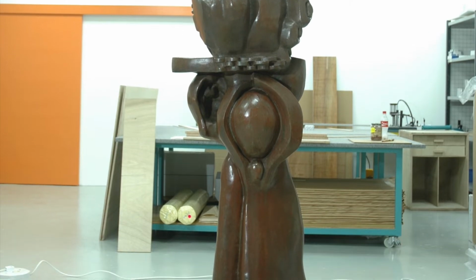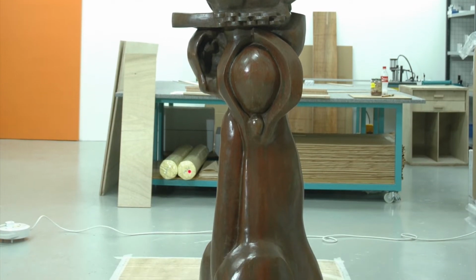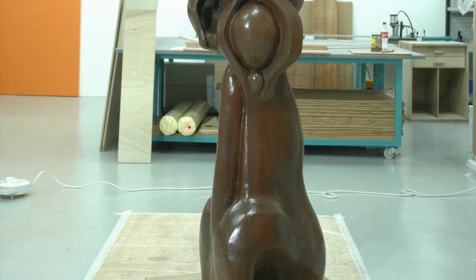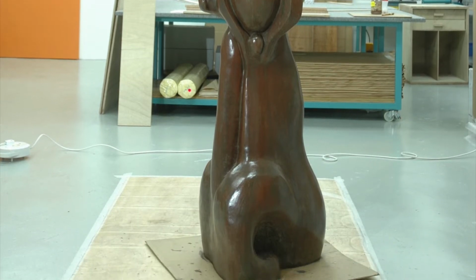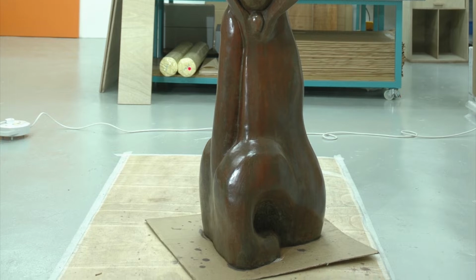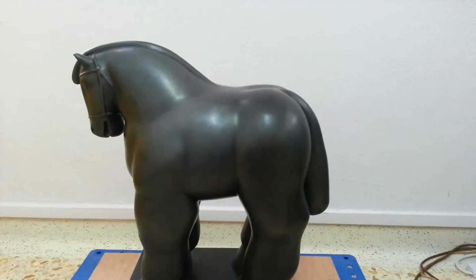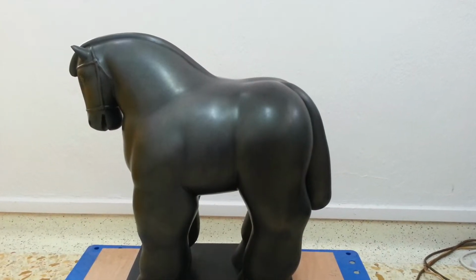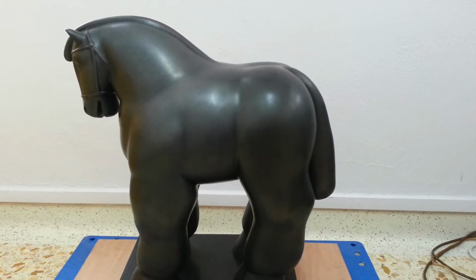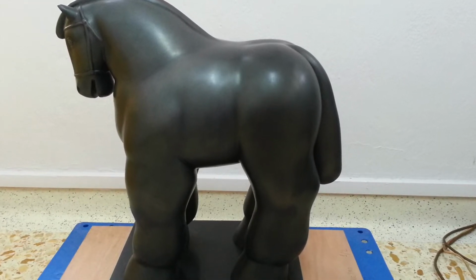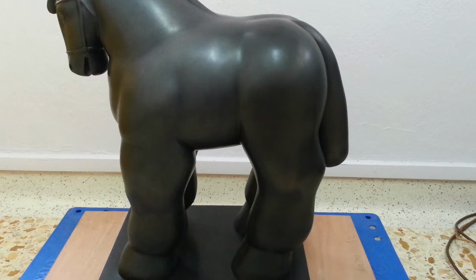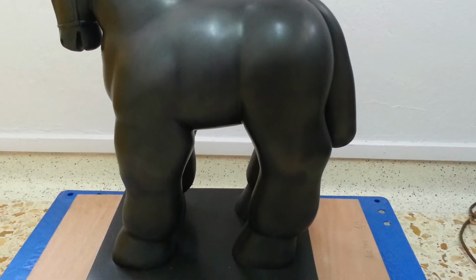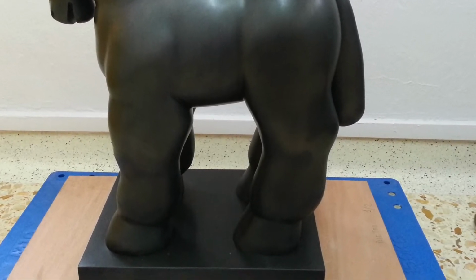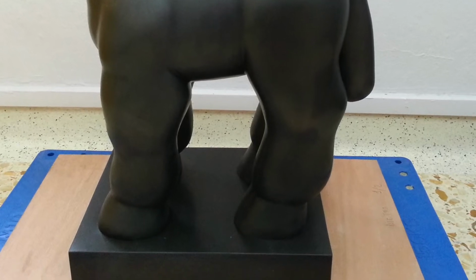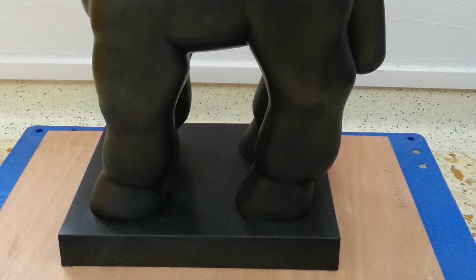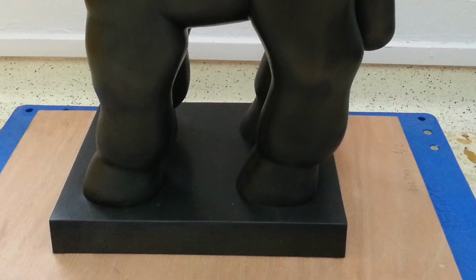A bronze containing chloride corrosion, due to previous exposure to a chloride environment such as a coastal climate, can still corrode in an indoor environment. These chlorides can be due to burial, as in the case of archaeological bronzes, or in contemporary bronze sculptures due to airborne salts, handling and others. This chloride corrosion can be indicated as light green to turquoise spots, powdery or solid in texture, or even as a light green liquid when exposed to high humidity.